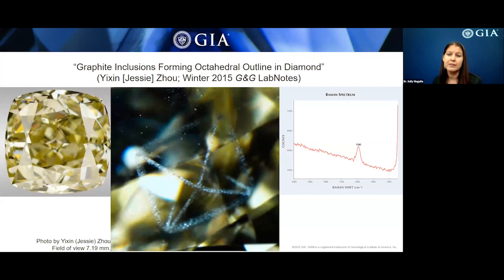Gemological examination revealed that the octahedral shaped inclusion is outlined by numerous irregular crystals. Raman spectroscopy, like I show on the right, shows that the inclusions are graphite with a Raman peak at 1590 wave numbers. Graphite inclusions are often seen in diamonds as isolated crystals or as part of crystal clouds. Here, these minute inclusions formed at the junctions of the original diamond crystal faces and outline that octahedral growth pattern. The stone definitely shows the beauty of formation of crystalline diamond and is a wonderful surprise within this fancy colored diamond.